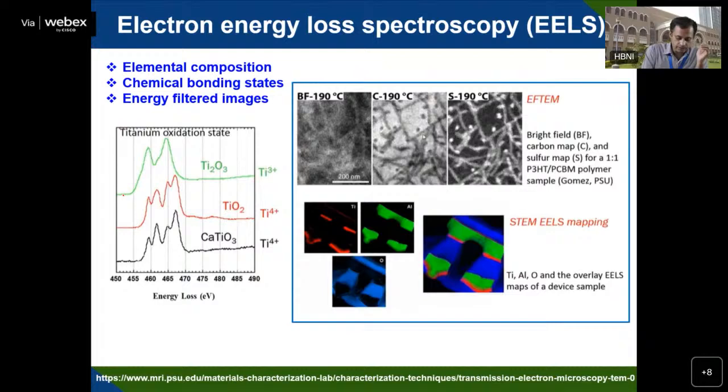You can see the titanium oxide, you can see two peaks that you are getting. So you can see the titanium is in a plus three state, a plus four state. Those information you can get from the energy loss, the valence band structure, and you can get composition analysis for chemical bonding states. And then you can also produce images by electron energy loss spectroscopy. You can see the backscattered electron image and the bright field image, as well as